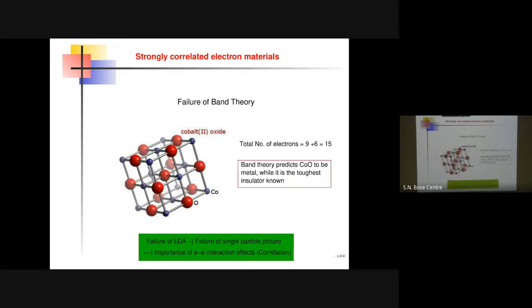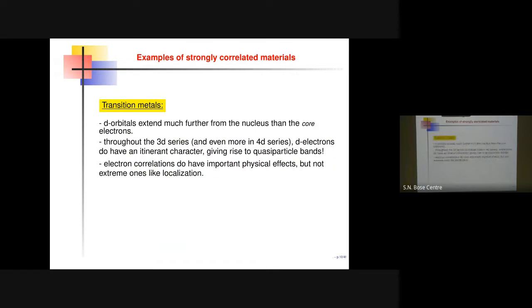I started with a certain concrete case. Take the case of cobalt oxide. You count the number of valence electrons, that's 15, an odd number. According to band structure, it should have been a metal, but it is possibly one of the toughest insulators known. So there is certainly a failure of the simple first principles band structure within the framework of density functional theory. So what are the examples? One example can be a transition metal with a d electron. Why the d electron?